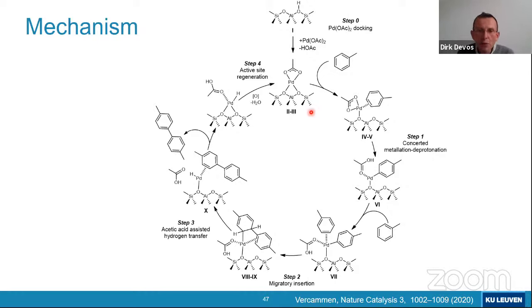Because in the activation of the first arene, there is still this acetate which can assist the palladium in activating the toluene in a concerted metalation-deprotonation. So the first step is indeed such a CMD step in which the acetate as a base will pick up a proton from the toluene.